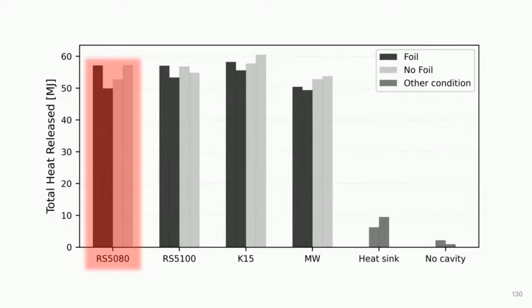Despite the earlier escalation to full involvement of the Renabond PE when the foil facers were removed, that I just mentioned, these data suggest, in this plot, very little difference in the total amount of energy released up until local burnout of the cladding system, i.e. during the 20 minutes of the experiments that we performed.